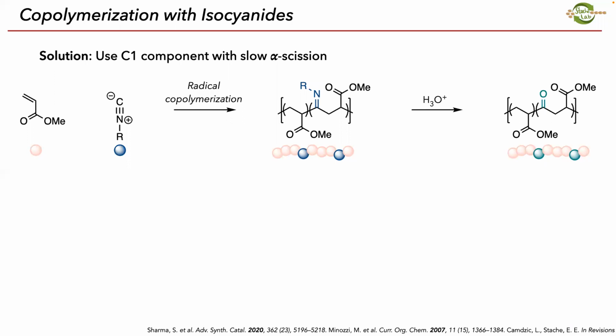And so what we decided to do is use isocyanides, which are isoelectronic to CO, meaning functionally they're very similar, they react the same, but they don't react the same in every facet, meaning they don't undergo that reverse decarbonylation reaction. And so in that way, we can generate this polyisocyanide, which is functionally very similar to the polyketone, and we can remove this group by just treating with a little bit of acid and water, to reveal the polyketone that we want. And so we can generate these polymers by using this other type of